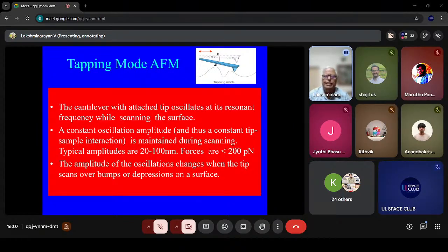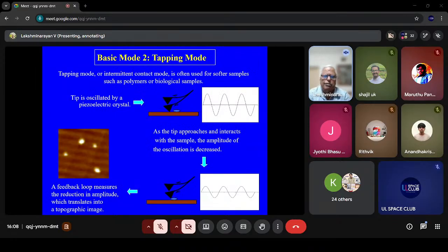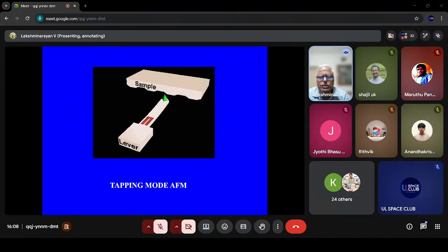In the tapping mode, the tip is intermittently tapped, and during the tapping the resonance frequency changes, and then the amplitude changes, and that amplitude is maintained constant. This is very popular because it gives a much better way of imaging, and it also doesn't damage the surface because it's not continuously in contact. So this is what's called tapping mode AFM, and it is used for polymers and soft materials and all those things.